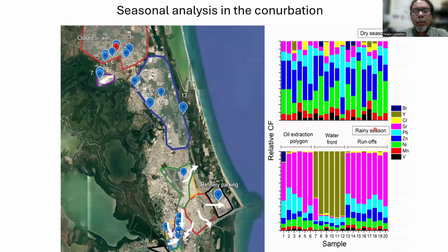Also, we have 20 points collected in both the dry season and the rainy season, where we compare the amount of these metals: bromine, yttrium, chromium, strontium, lead, zinc, nickel, manganese, and vanadium, which, as you can see, vary very much, with very different relative concentrations between the dry season and the rainy season. The amounts of strontium and yttrium increase a lot after the rain, which indicates that these pollutants were suspended in the air during the dry season. And also important contents of chromium are observed in both seasons, manganese also, and vanadium. So these variations come from the points where these powders were collected.